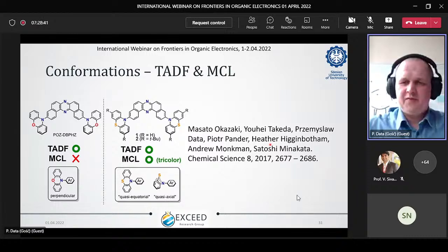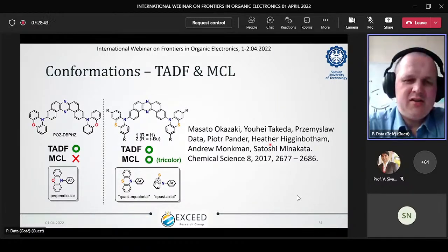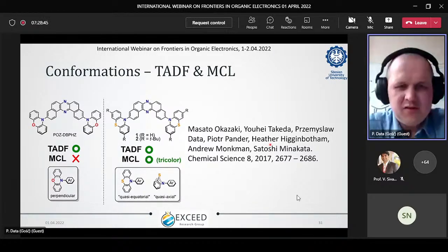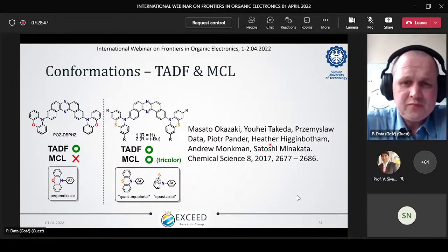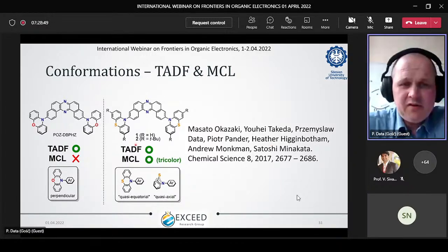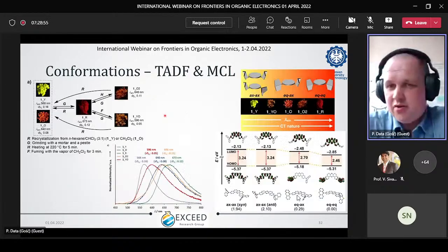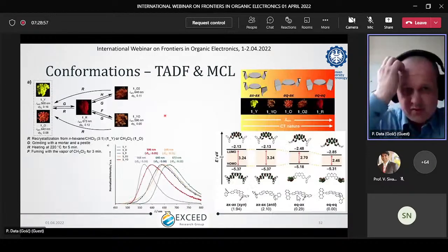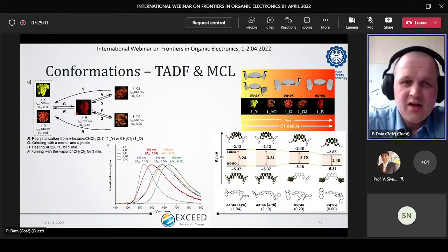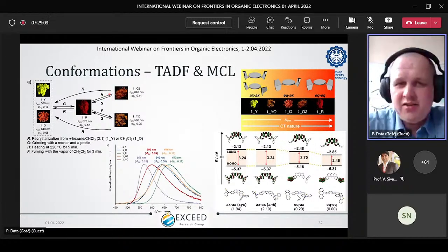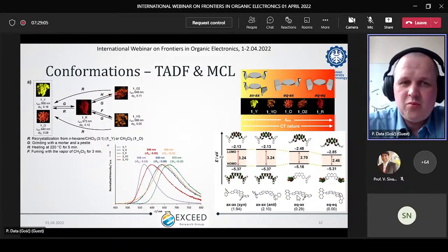The other factor is conformers, which we found during our analysis with my colleague, Professor Takeda from Osaka University. He sent us several different molecules for analysis. And what we found out is that some of them had mechanochromic properties. In the beginning, we were not sure what the reason for this was, but the mechanochromic process is the process where we are adding energy, in the form of grinding or fuming, and our material changes conformation.